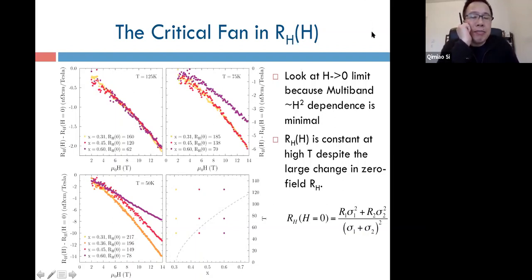Maybe I can ask a question following the lead you were giving towards the end of your talk, connecting different materials. The Hall coefficient in heavy fermion quantum criticality and in vanadium doped chromium seem to have very contrasting behavior, and there are various ways of analyzing it. But one way that has been fruitful for comparison is to look for the isothermal dependence of the Hall coefficient and see whether, first of all, there's any rapid change in the vicinity of the quantum critical point, and if so, whether there's a sharpening as a function of temperature.